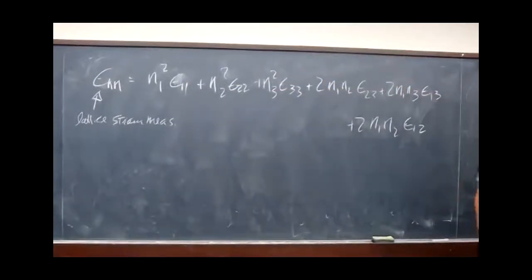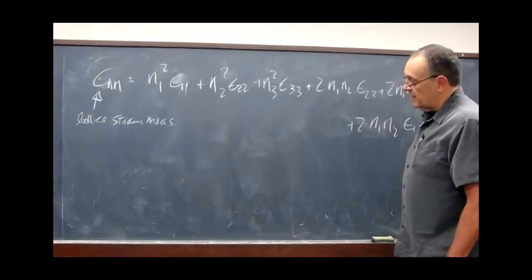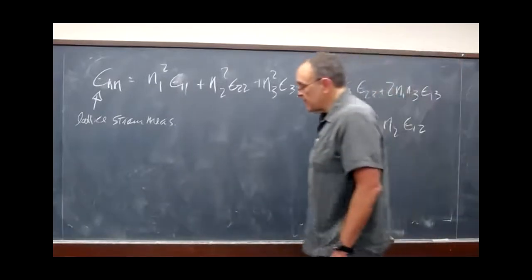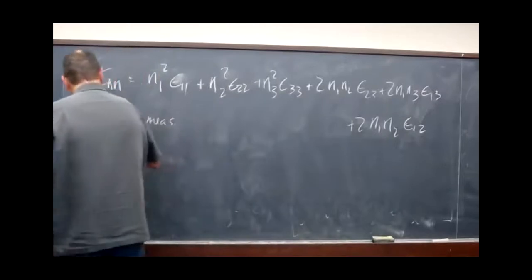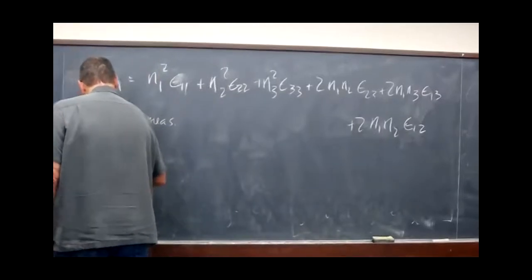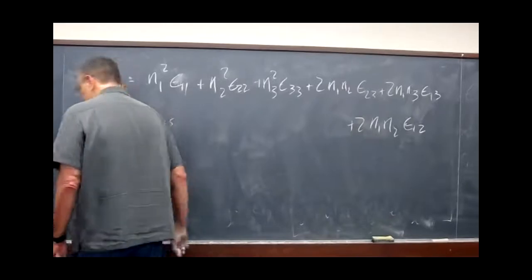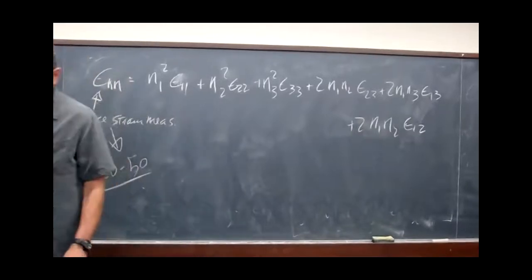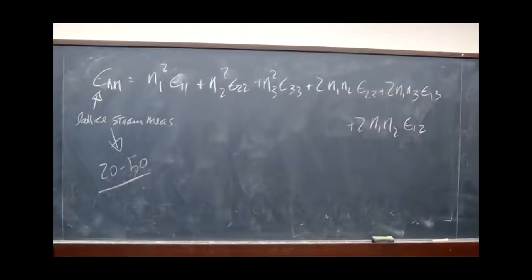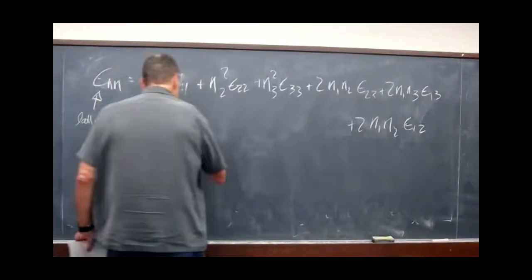But we're going to write this in a matrix form because remember, in a typical lattice strain measurement experiment, we'll have 20 to 50 of these, maybe more, depending upon crystal class and just how far we rotate our sample. So we're going to have lots of these, and now we need at least 6.